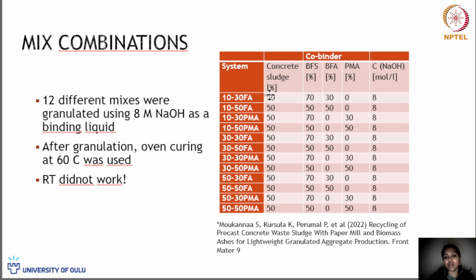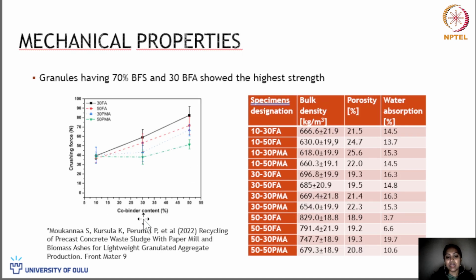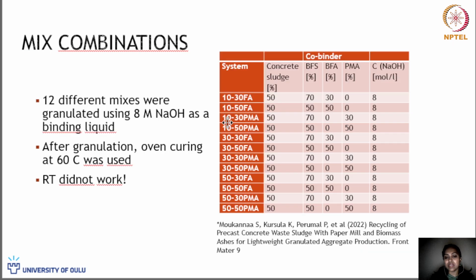And in all the mixes, the amount of concrete sludge was maintained as 10 to 50%. Sorry, there is a mistake here. So 10 indicates 10% of the concrete sludge, and then 30 indicates 30%, and 50 indicates 50% of the sludge. Among co-binders, this is the percentage of co-binders that has been added. So 30% FA means 30% of fly ash, 30% PMA means 30% of paper mill ash, and the remaining co-binder is blast furnace slag.